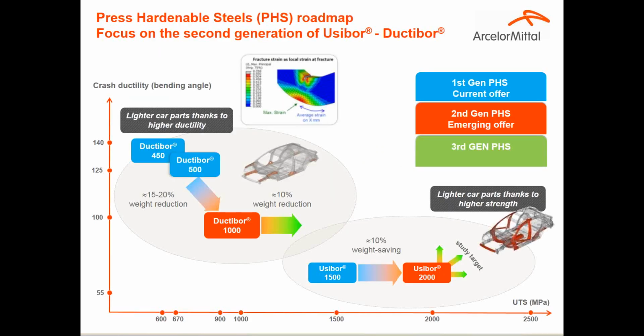Focusing on hot stamping grades, that today is well known, in hot stamping we are using grades that, after heat treatment and after stamping, achieve the right mechanical properties. You see in blue the current materials used: Ductibor 450 and Ductibor 500 for energy absorption, and Usibor 1500 for anti-intrusion. The key advantage of hot stamping is the formability, because we stamp at high temperature.